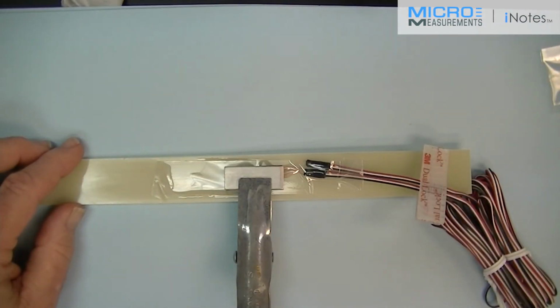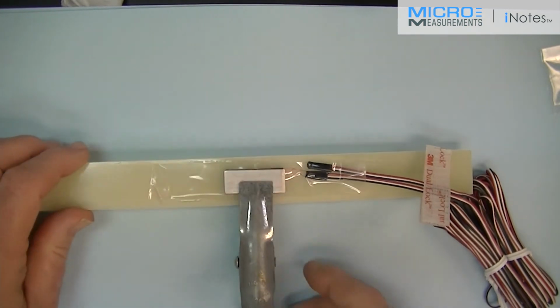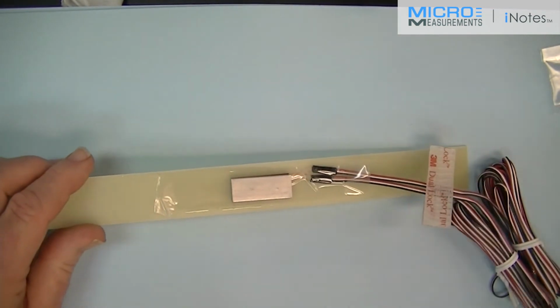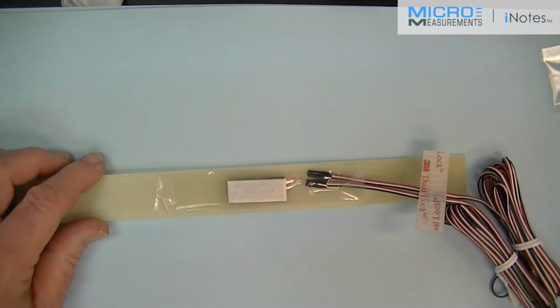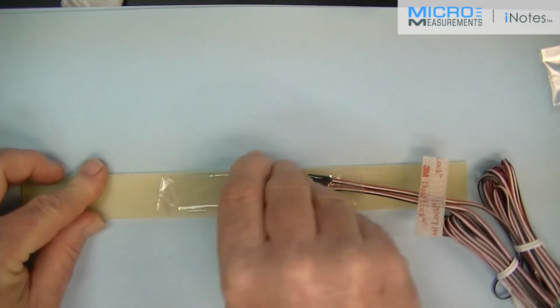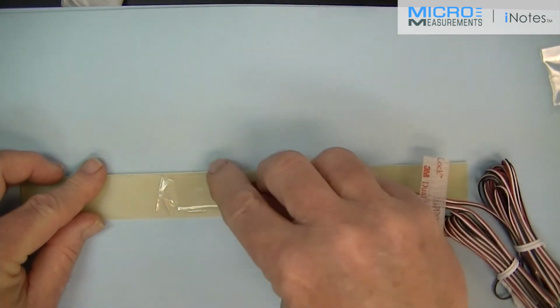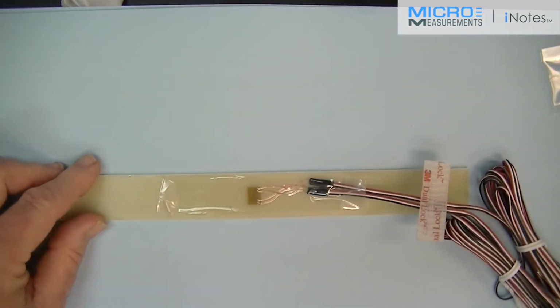Our curing process is complete, which was 6 hours at room temperature, or it can be elevated to up to 200 degrees Fahrenheit and accomplished in 30 minutes or less. First off, we're going to remove the clamping fixture, the Hargrave clamp, the aluminum backing plate, and the silicone gum pad.